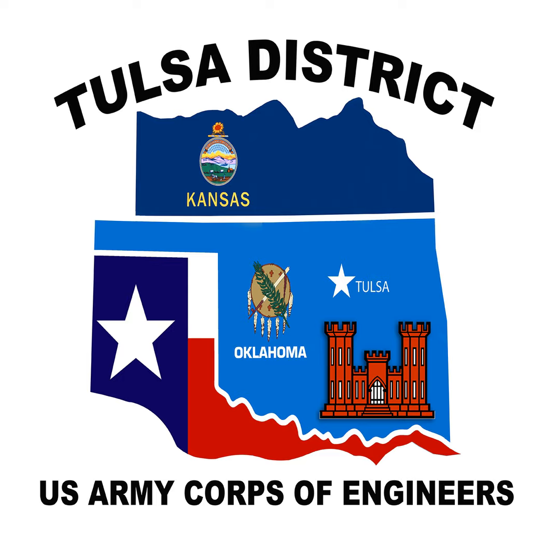And you guys can build your own beams here, right? So we have the facilities here to do fairly large scale concrete construction. And these beams were pre-stressed beams, which is typical for bridge girders. And we have a pre-stressing setup here at FEARS Lab that we can do up to 6 pre-stressing strands at a time. So we can get a pretty good scale size beam. We can never build a full size beam, but we can build small scale specimens to test in the lab. So, and you said that the corrosion actually adds some strength at least on the front end, right?